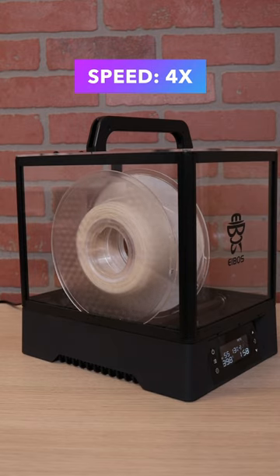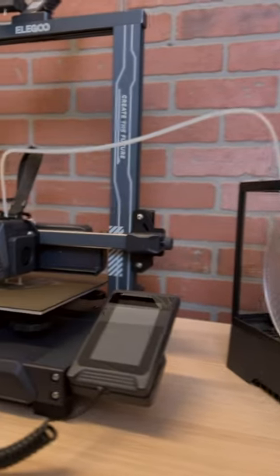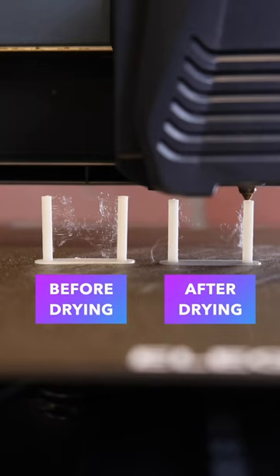I wanted to test the impact that one drying cycle would have, so I ran the spool for four hours at 50 degrees Celsius and then ran the same calibration test again.